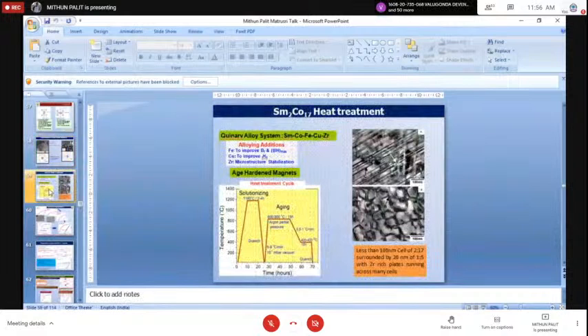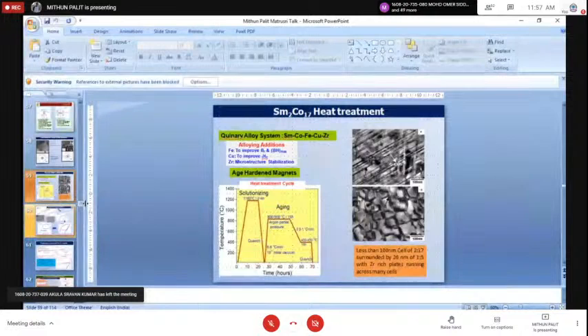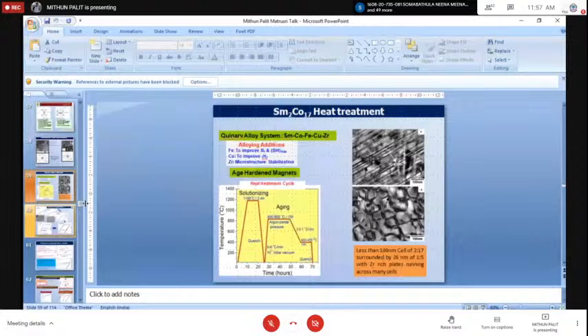For this particular 217 class of material, we follow a very complex heat treatment because it has a 5 element system: Sm, Co, Fe, Cu, and Zr. First, we ensure that every solute is in solution at 1180 degrees or so. We do the solutionizing. Subsequently, we quench the material to retain all the solutes inside the material, and then we do a controlled heat treatment called aging, so that the desired morphology and volume fraction of the strong pinning precipitates come. So the efficacy of this heat treatment is very important.